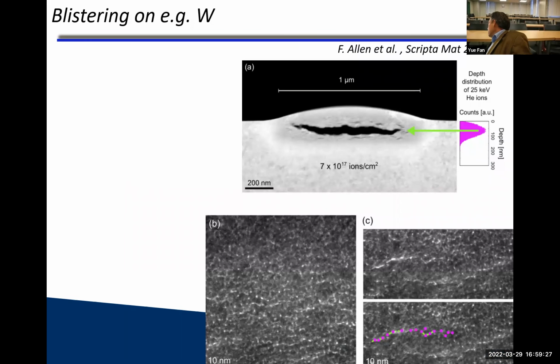And last but not least, I was going to talk about these blisters for a second. So we see these little bumps, the cross section of these bumps. This, however, is not copper, so I apologize for that. This is tungsten. I don't have quite the same nice picture for copper, unfortunately. But for tungsten, you see these same beautiful blisters, and you see these cracks forming here, and lots of small cracks too. In TEM, if you look at the small helium bubbles, you actually start seeing those things connect. And tungsten is a reasonably brittle material.